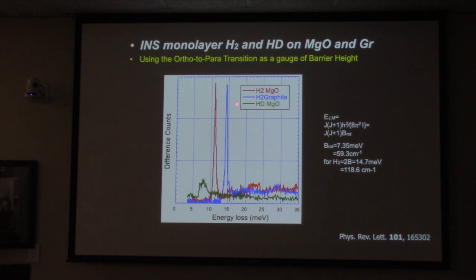Anyway, this is the ortho to para transition. It's a rotational transition that you can measure for hydrogen on magnesium oxide, hydrogen on graphite. This is basically where the bulk ortho to para transition shows up. If you're a chemist, you like about 120 wave numbers. If you're a physicist, you like about 15 millielectron volts. You choose. But when you put it on magnesium oxide, it turns out that the molecule is hindered a little bit, and so it reorients a little bit slower.